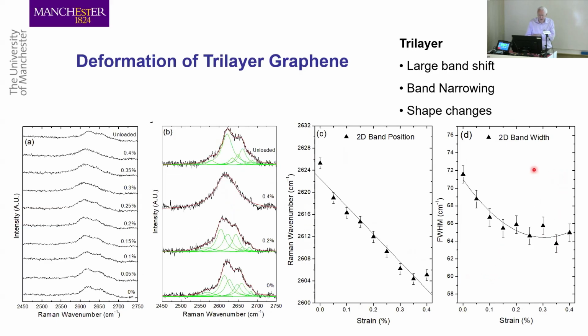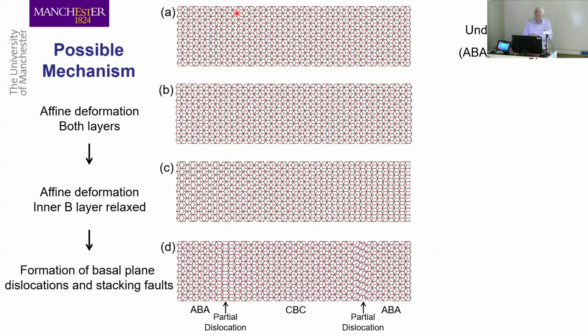But trilayer is very odd. In trilayer, you get a peak shift down of the peak position, but when you look at the peak width, it actually narrows. So you've got the trilayer narrowing where the monolayer and bilayer broaden. So you've got changes in band shape with strain. Well, that may be rather subtle, but it's telling us that something's going on, which is quite interesting. And what's happening is the layers can't slide over each other very easily. And you get this band narrowing, which is rather odd. So we have different mechanisms here.